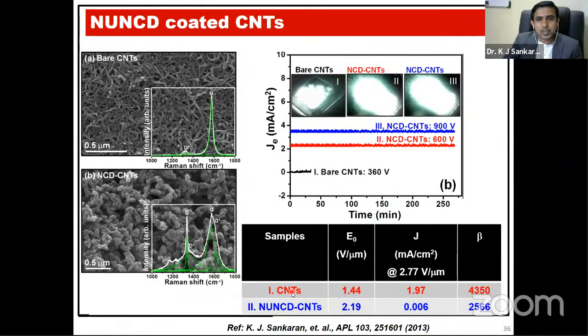But the lifetime stability is the important matter here. When you apply a low voltage to the carbon nanotubes, only carbon nanotubes, it can go only up to 30 minutes. But when you apply high voltages like 600 and 900 volt, which achieve a very good uniform electron emission and can withstand for longer lifetime, even more than 250 minutes with a very good field enhancement factor. So the NUNCD, which is coated on the carbon nanotubes, achieves a very good lifetime stability with very good field electron emission display.